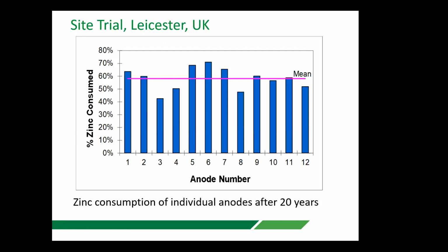We looked at how much zinc we actually consumed over the time period. We did that both ways. I measured the amount of charge that was delivered by the individual anodes, used an efficiency factor of about 70%, and determined how much zinc was consumed using the Faraday equation. And we saw that after 20 years, we roughly used about 60% of the zinc within the individual anode. You can see number 3, which is the one that was struggling.